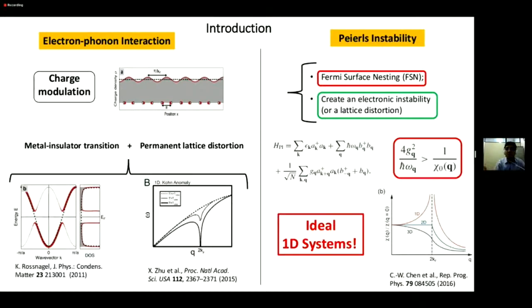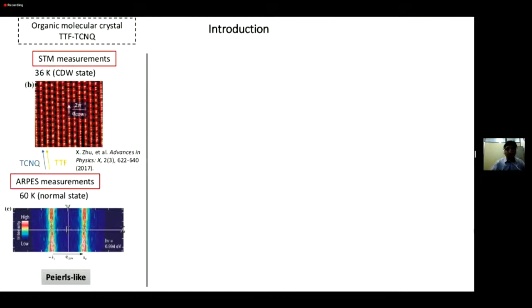Basically, you cannot have a normal metal. You create this long range order because your system is quite susceptible to any perturbation. In fact, it works in particular for 1D compounds, but we can discuss it in more detail. And it works in real compounds. It happens in real compounds. For instance, here is one example of STM measurements in this quasi-one-dimensional crystal. This is an organic crystal. Here it's difficult to see from the figure, but actually we have two chains here.